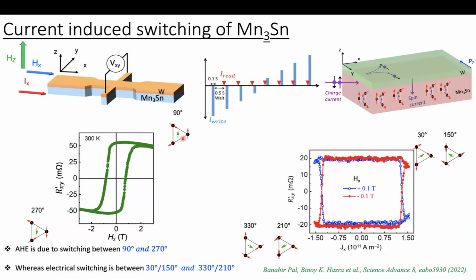Later, I think the Nakatsuji group and other groups also induced some uniaxial strain in the system and stabilized one type of domain, let's say 90 or some other domain, and then they observed full switching as well. I see. So here there were six domains, and they play different roles in field induced switching and current induced switching. But if you have one type of domain, then that will contribute to both.